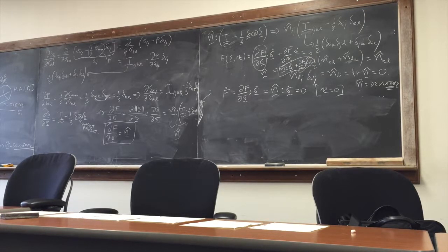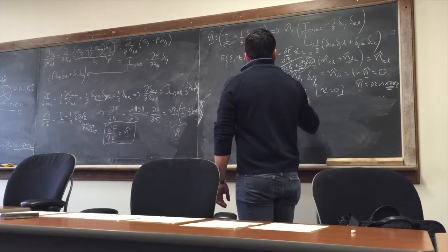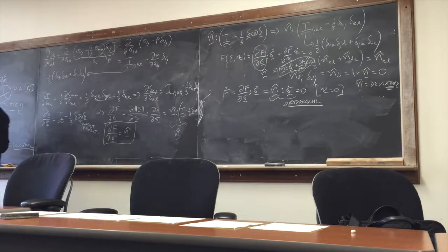Again, make an analogy with vectors. What does it mean for n hat double contracted with sigma dot equals 0? If these were vectors, they would be orthogonal, right? This would be an orthogonality condition. So if you go back to your principal stress space and you see n hat as a tensor, as a vector, that gives you a sense for the possibilities for sigma dot. What your consistency condition is telling you is that sigma dot needs to always be orthogonal to n hat, right?